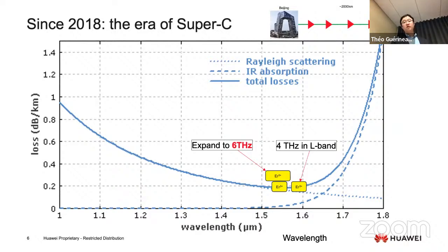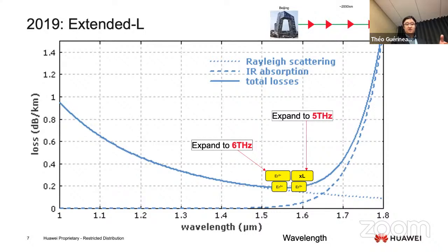And then we moved our sights to the L band. Since 2019, we started to work on the L band. We want to copy the success in the C band and expand the bandwidth in the L band. Then this is again about the material, because usually the erbium doped fiber glass matrix is aluminosilicate glass. But for erbium in aluminosilicate glass, the emission bandwidth is very limited. It's limited to 1615 nanometers. Beyond that, the gain drops very fast.